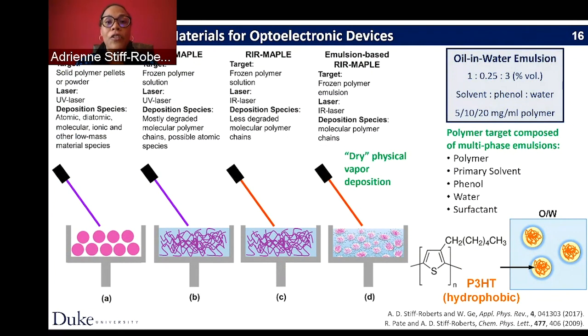Just to back up, people have certainly demonstrated thin film, vacuum-based physical vapor deposition of organic small molecules. People at Michigan have done that, Stephen Forrest. And that's very straightforward for small molecules because they are much more crystalline. They can be tightly packed and ordered because of their small size. They can be thermally evaporated without damaging that small organic molecule. And you can make very high performance devices. If you want to do the same thing with polymers, it becomes a lot more challenging. That's because the polymers have a much larger molecular weight. They're much bigger. There are many more opportunities for that molecular weight to be damaged. And that's a problem if you want to make the optoelectronic devices that I'm talking about, because as I mentioned, the size of that backbone, that repeat unit of single and double carbon bonds, is determining the extent of delocalization that you have in the electrons.